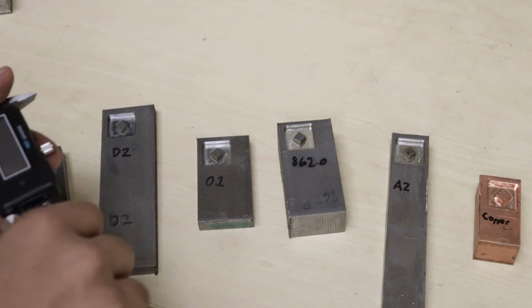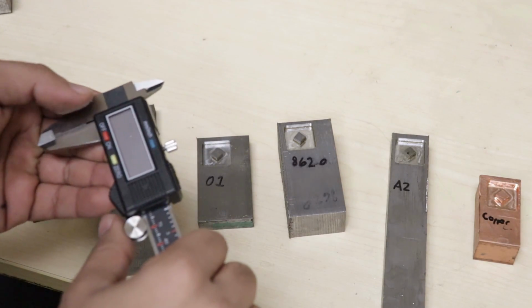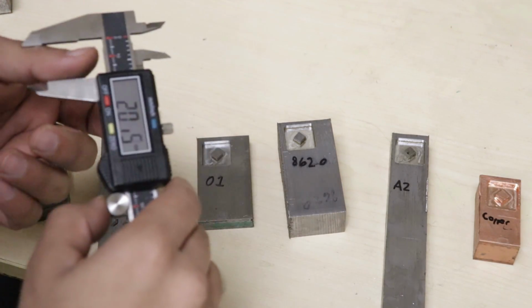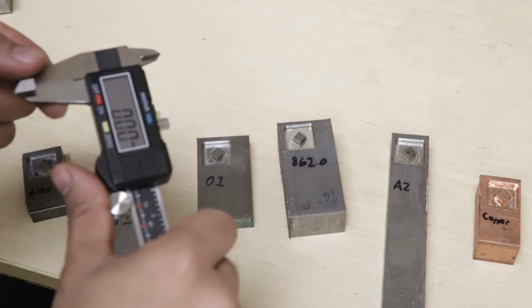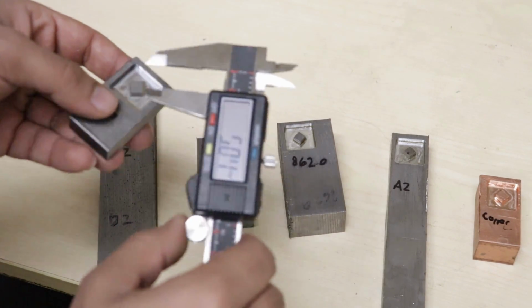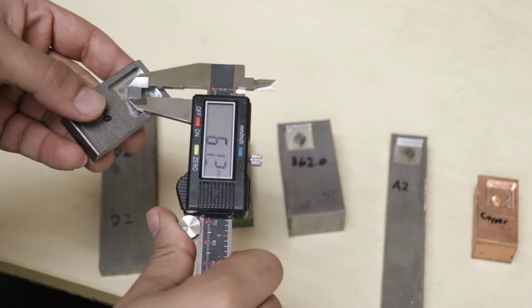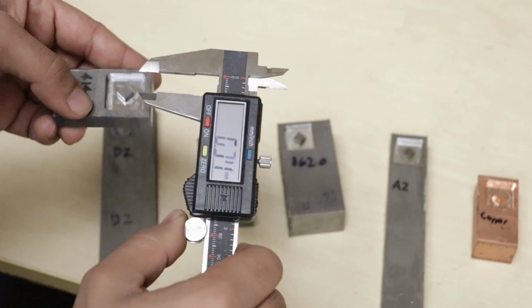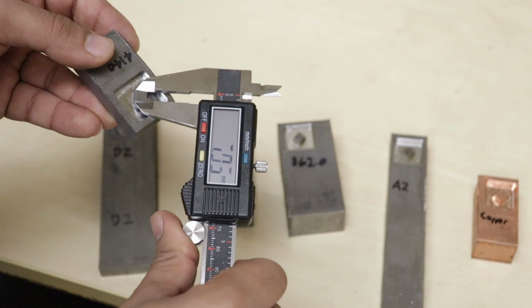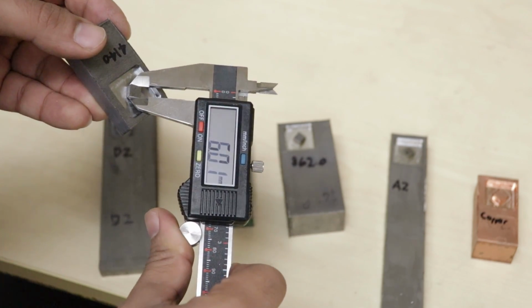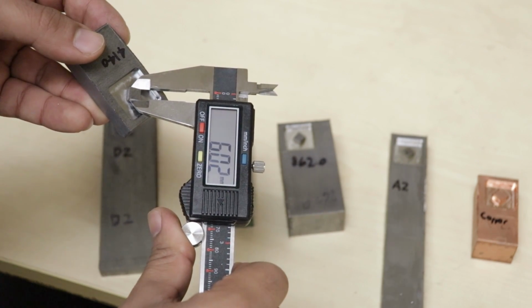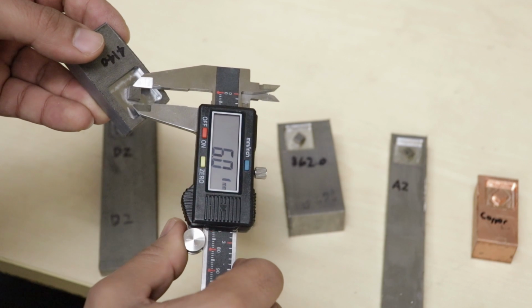So now measuring the inner square. These were machined with a very fine finish pass and should come out to 6mm across each flat. My calipers are nothing high-end, and this is definitely not the best way to measure, but it'll still give us a good idea of how accurate the parts came out. Measuring them all, they each come in at about 6mm plus or minus maybe 0.01mm, and that's excellent. Some of this deviation is maybe even due to me not holding the calipers correctly or consistently.